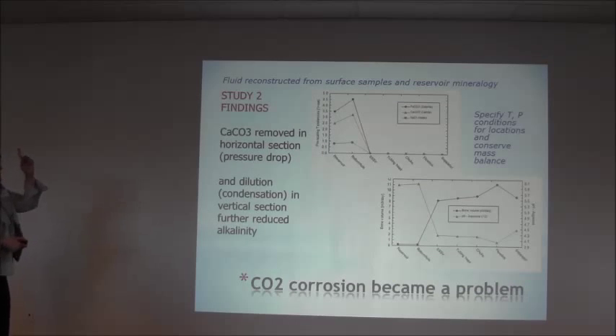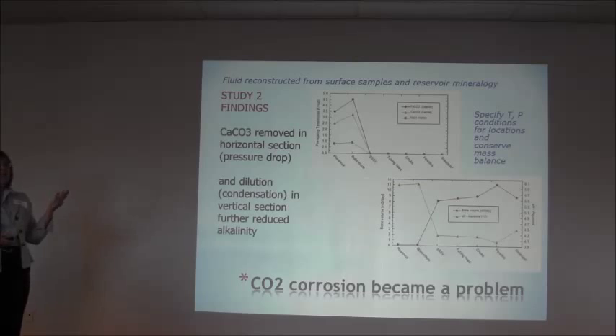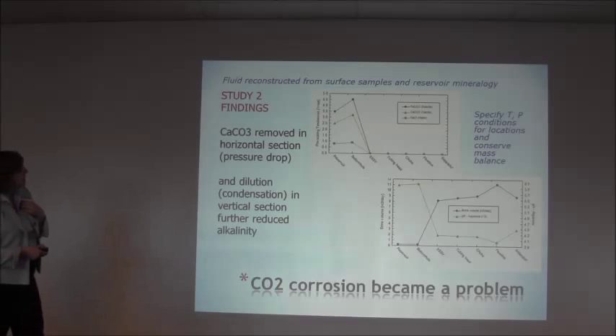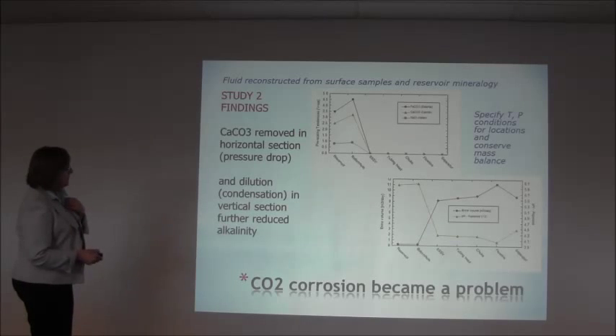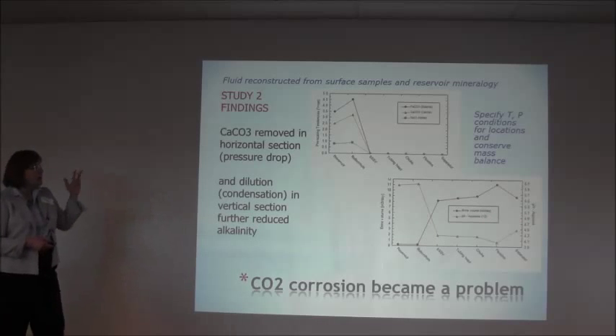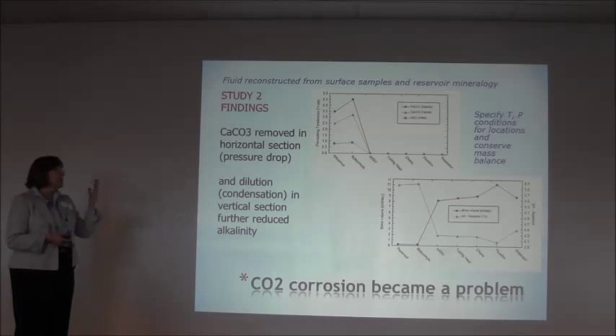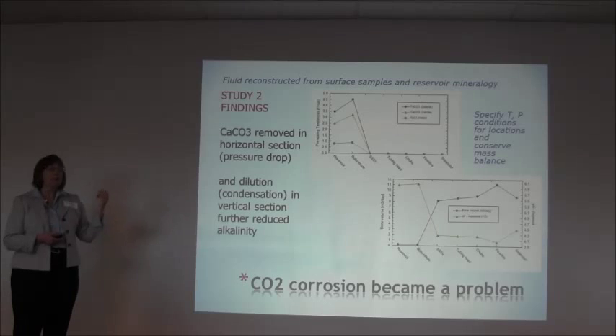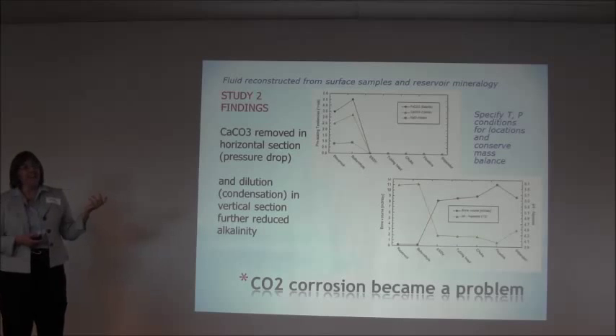Another thing that happened is as we came up that vertical pipe, it started to condense, and that further diluted the alkalinity and the pH. So if you look at the graph, you can see that the pH just kind of went nowhere. It's this lower one. The pH just kind of went down as first the carbonate left, and then the water came and diluted it. The moral of the story was that it was CO2 corrosion caused by lack of alkalinity, you can see.